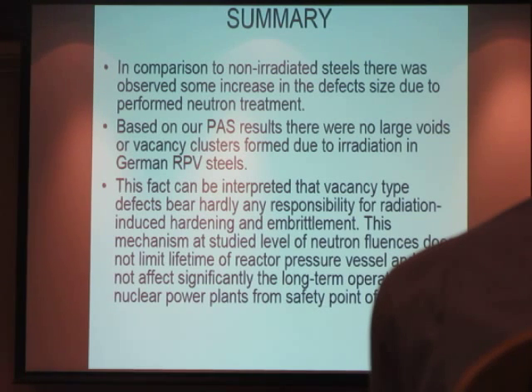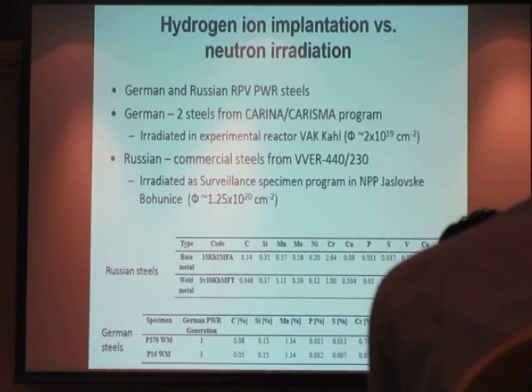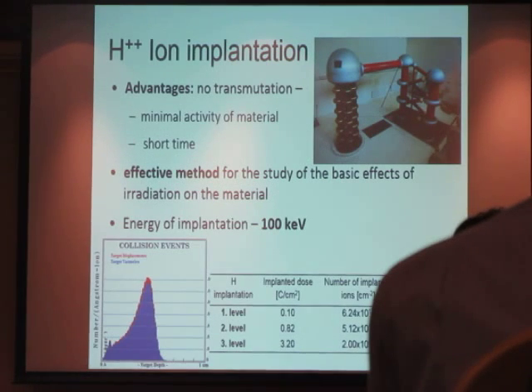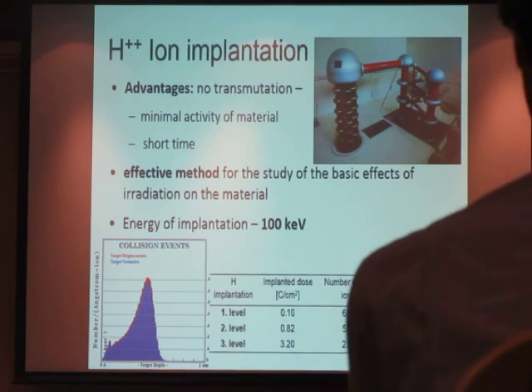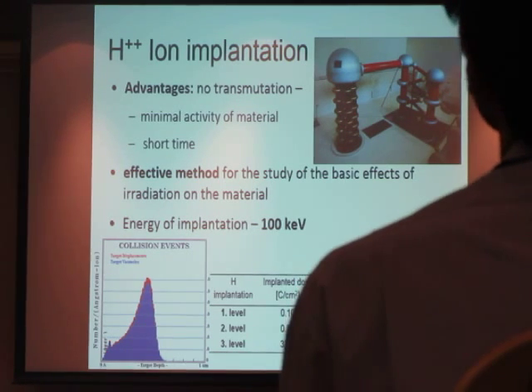This fact can be interpreted by vacancy type defects. They can hardly be responsible for radiation induced hardening and embrittlement. In the comparison between implantation and neutron irradiation, which was done between these specimens, we implanted hydrogen by our accelerator at 3 different levels. And we went up to higher implantation doses, but let's consider this 2 dpa.